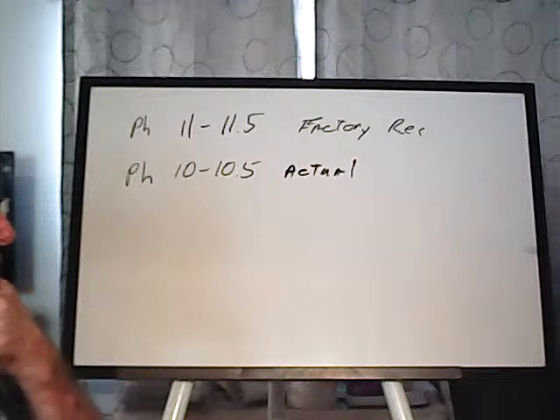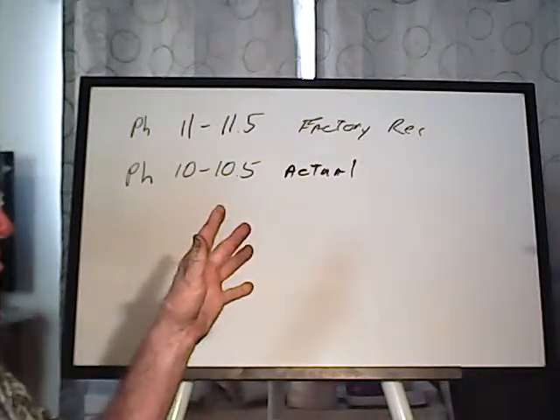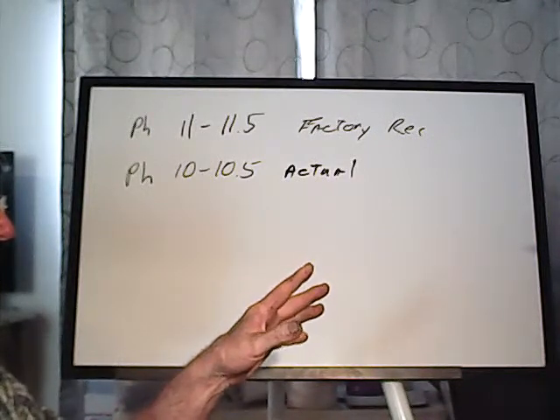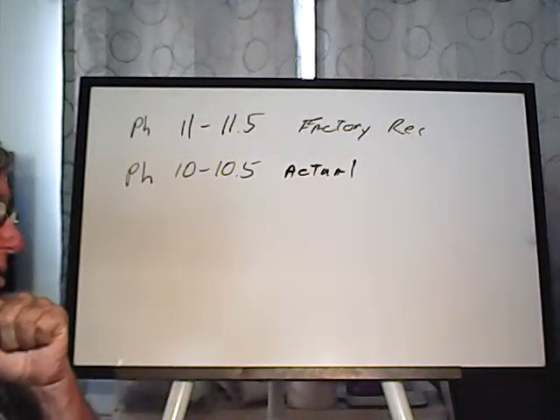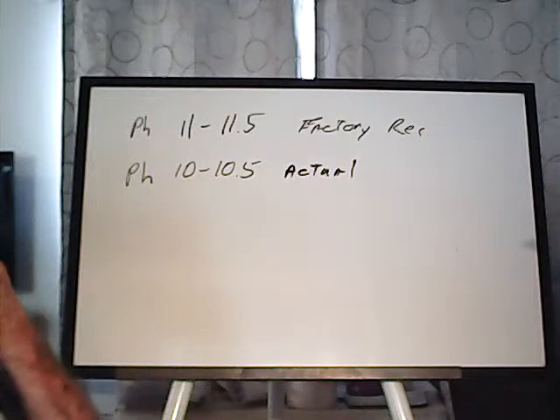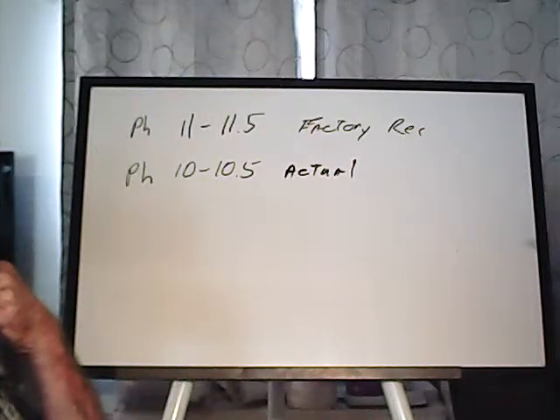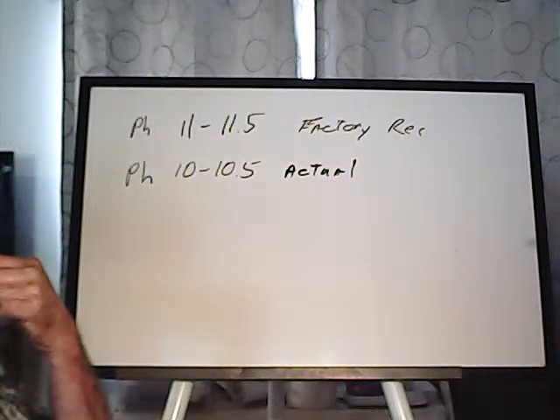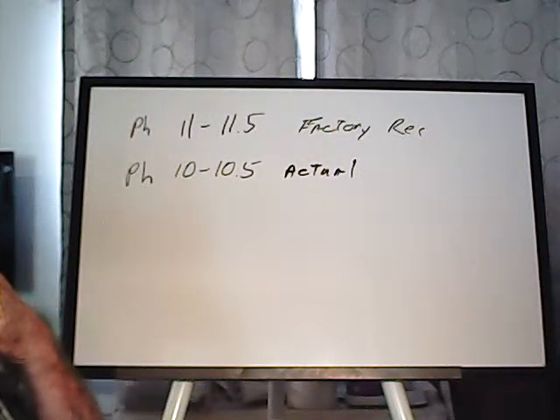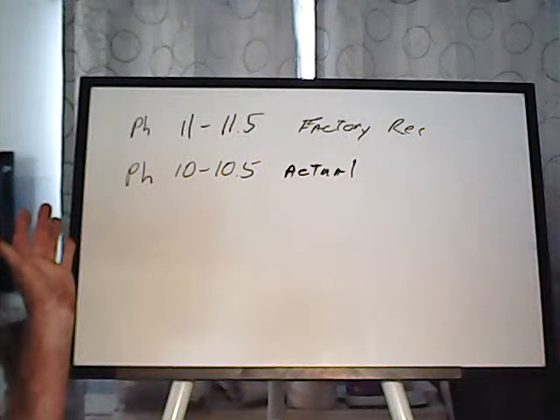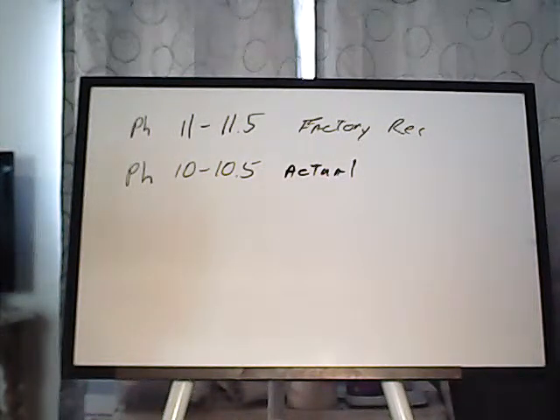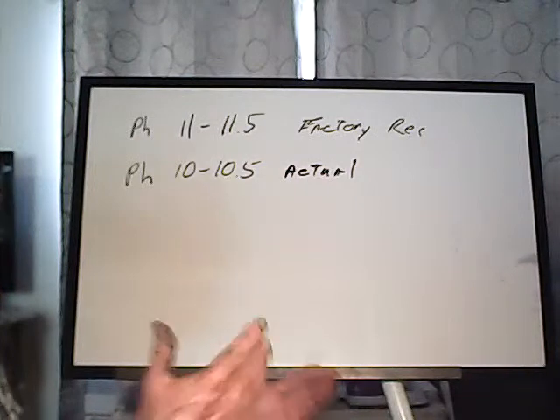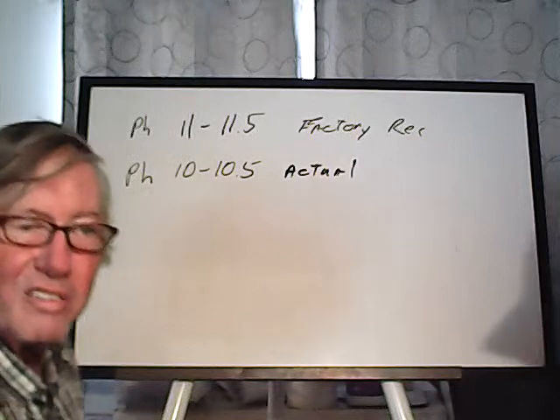Now, as long as we didn't poison the solution, I could lose the Eco Goldex that's still in solution to get the gold out of it, and it wouldn't be terribly costly compared to the amount of gold I would recover. Right now, I'm starting out at about 3 kilos per ton of solution, and I'm running about $3 per kilo. So we're looking at $10 per ton of solution, and each ton of solution is probably going to be gathering roughly half an ounce of gold. So that's $900. Yep. So $10 in chemicals for $900 in gold. Even if we lose it all, it's an acceptable cost. Yep.